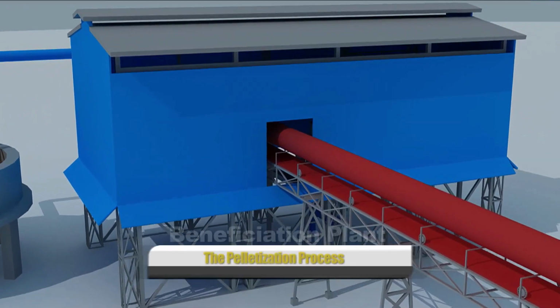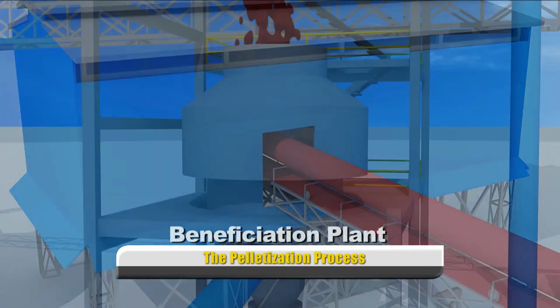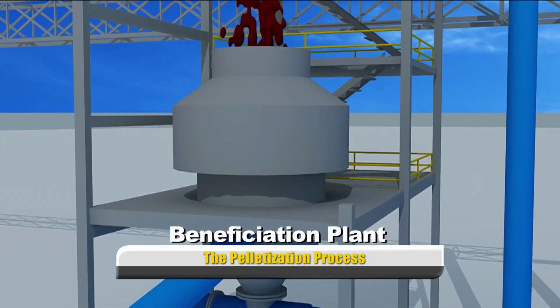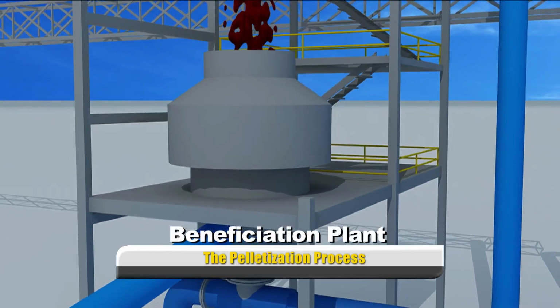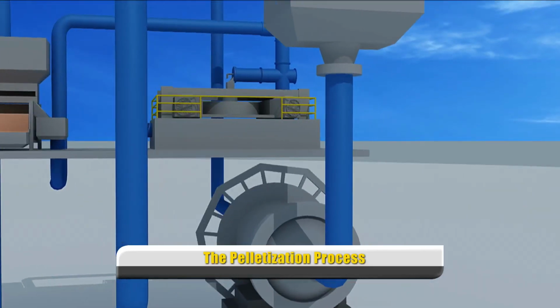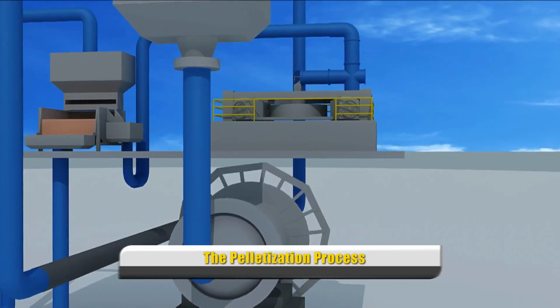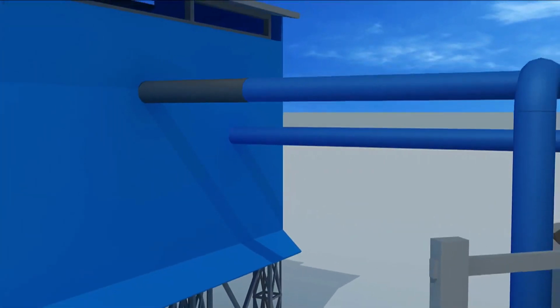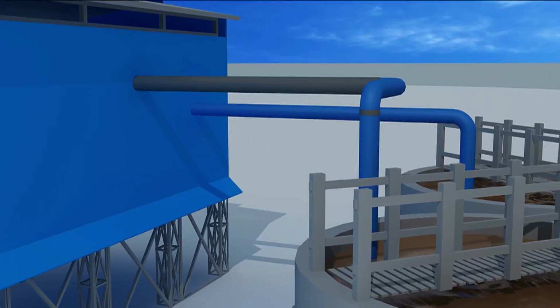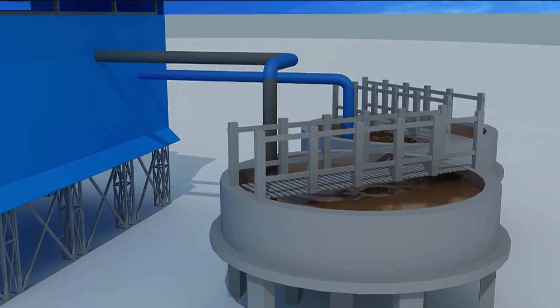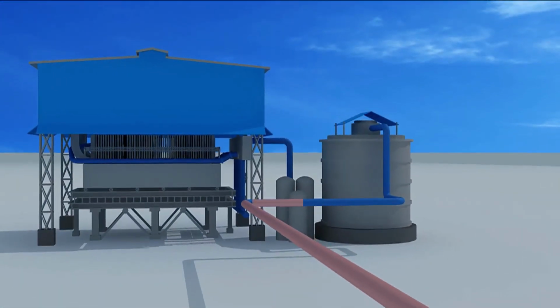Iron ore fines are processed at the beneficiation plant. Washing or magnetic concentration method is used. Then the iron ore fines are dried. The dried fines are passed through a ball mill to grind to a predetermined size, which is normally minus 200 mesh. These ground fines are stored in a bin.